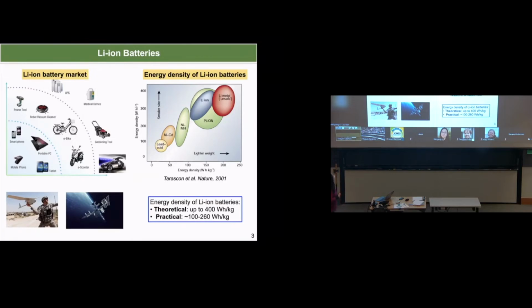Lithium-ion battery also has been widely applied for military applications such as drones, and for space application. If we look at the energy density that the current lithium-ion battery can deliver, the theoretical energy density is around 400 watt-hour per kilogram. And if we look at the reference here, this is back to 2001. Even though this is almost 2 decades ago, there's really not much improvement in terms of the lithium-ion battery. So the practical energy density we can get is around 100 to around 260 watt-hour per kilogram. This is the best record on market right now.